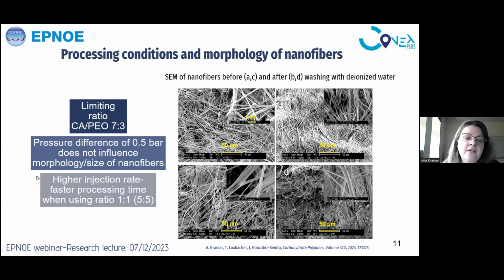And we found that we can use higher injection rates, which means faster processing time, if we use the same ratio of cellulose acetate to PEO, 1:1 or 5:5. So here you can see in A and C scanning electron micrographs of nanofibers before and after washing with deionized water. And we were very happy and excited when we washed our non-woven materials and saw that we actually preserved the nanofiber morphology.